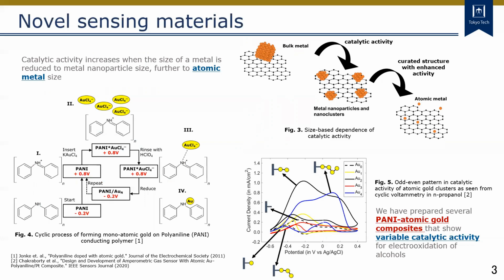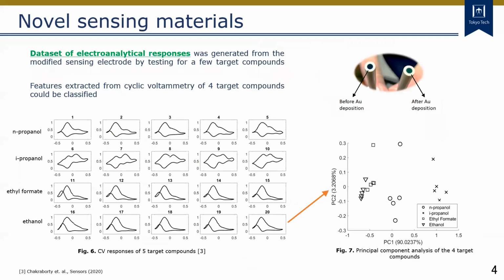In our group, we have prepared atomic gold nanocomposites with different numbers of gold atoms. Such nanocomposites exhibit an odd-even activity, which was confirmed with cyclic voltammetry of electrooxidation of alcohols in alkali medium. A dataset of electroanalytical responses from 4 target compounds towards lower aliphatic compounds reveals unique oxidation peaks. Principal component analysis is capable of discriminating between the different target compounds.